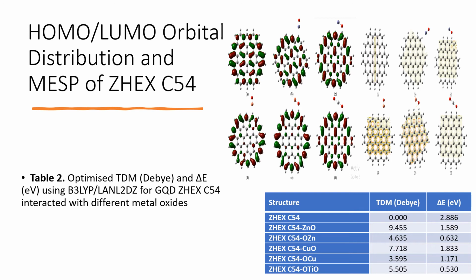In the case of graphene quantum dot zigzag hexagonal, metal oxide changed the orbital distribution and the color map of molecular electrostatic potential also changed, with an increase in red color, which increased the reactivity of the graphene quantum dot surface. Also, total dipole moment increased while band gap decreased with the decorated graphene quantum dot with metal oxide, and the most enhanced metal oxide is titanium dioxide with band gap equal to 0.5.